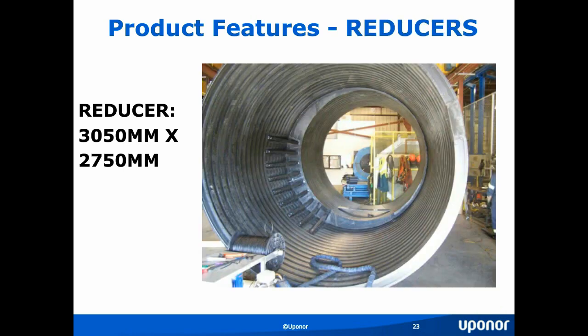In this picture, you are looking at a reducer. And this particular reducer is going to a power facility on Vancouver Island. And it's reducing down from our 10-foot diameter Weholite down to our 9-foot diameter Weholite. And you can see those bars on the inside. That will eventually be plated over, in order to allow a nice smooth transition from the 120 down to the 108. You can see in this picture as well where we have aligned up the inverts of the 120 and the 108 inch, and therefore creating that sort of step in the reducer. So if we didn't plate that over, we would have that step. And of course, with your flow characteristics, you can't have that, especially in a power project. So that's why we will plate that over and make it a nice, smooth transition.